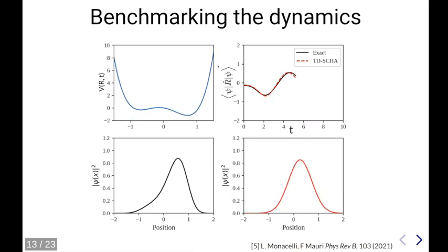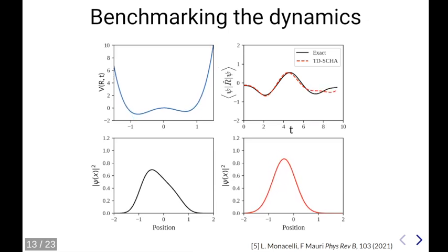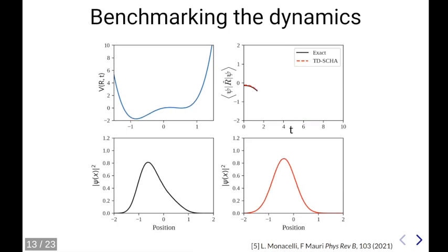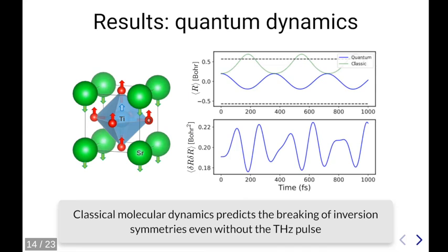The difference with respect to the exact result is that we can employ this theory to simulate a much bigger number of atoms, up to hundreds even, and that's exactly what we did. For example, if we take only one phonon mode, which is the ferroelectric soft mode of strontium titanate, and we displace it and do the quantum dynamics, we can see that it evolves around zero because it's a quantum paraelectric.